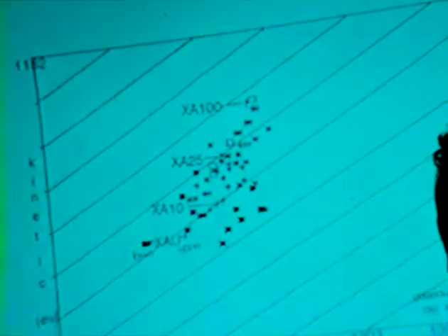And going back to the carbon fiber story, here we see how the change in the Auger parameter, the relaxation energy, is changing. These lines represent the Auger parameters, from one which is unoxidized, down here, to one which has had a standard treatment. It's called 100%, but it's a standard treatment that's used in industry, with intermediate ones in between. One interpretation of that is that the atom which we put onto the surface to decorate the surface is actually being drawn closer and closer into the surrounding atoms as you go up in degree of oxidation.